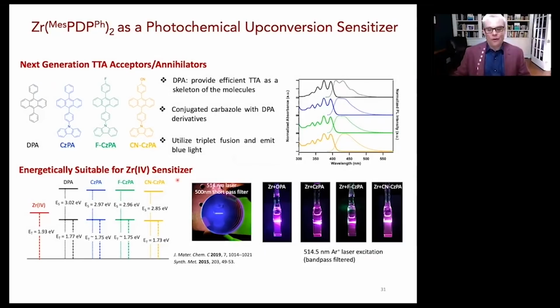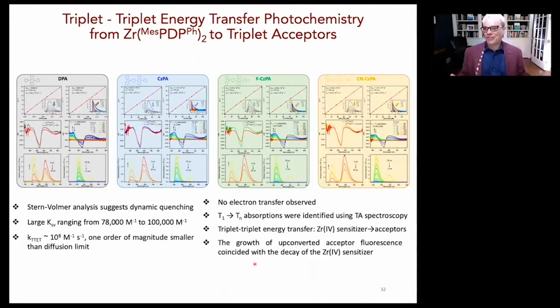Ultimately, we combined all of this together, and you can very clearly see upconversion in all facets. But I figured in this particular project, I would go through a little more detail because I've only been showing you pretty pictures, but I want to tell everybody there's a lot of spectroscopy behind all the pretty pictures. So in every case, you have to do Stern-Volmer analysis, both static and dynamic, and make sure that your rate constants match, because you have to have dynamic Stern-Volmer quenching to really make this work as well as possible. All of these have massive Stern-Volmer constants. That's really great. So this means energetically downhill, but very fast and very efficient energy transfer in the first step.